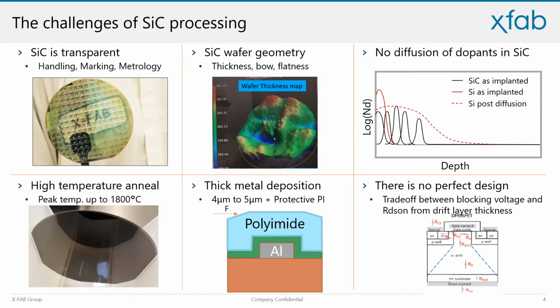The second challenge is the wafer geometry. Silicon carbide wafers have a huge bow and roughness compared to silicon wafers, but are only half as thick. So imagine you try to place a bowl on a flat tray and do some lithography with the same focus depth over the whole wafer. You will fail. And we have the thermally induced bow. Once you heat up the thin silicon carbide wafer, they double bow like a potato chip. Our engineers did a remarkable job at those tools. They managed to get the yield loss on those tools way below 1%. The equipment manufacturers supply the same tools with their best-in-class process with around 25% yield loss.